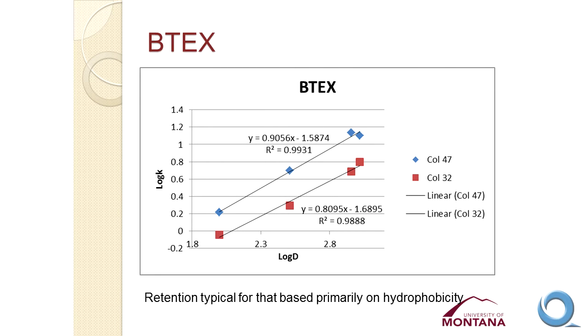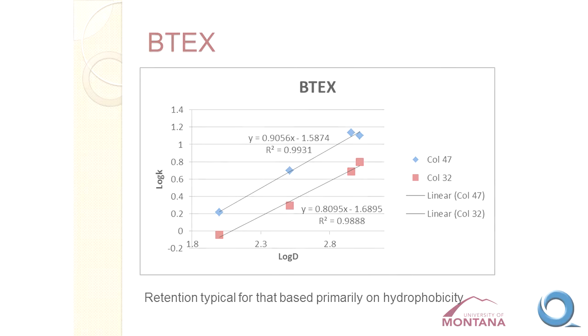We're interested in what really is the mechanism of retention. So we looked at a few different things with all of these studies. One was we looked at the logarithm of that retention factor as a function of the logarithm of the octanol water distribution coefficient. And what we see when we make these plots is linear plots, a linear relationship between log retention factor and log partition coefficient. And that's typical when the primary retention mechanism, the primary interaction mechanism, is based on the hydrophobic nature of the molecule. So it looks like we're really seeing a hydrophobic interaction, reversed phase type material, but with much weaker interactions than what you have with C8 or C18.